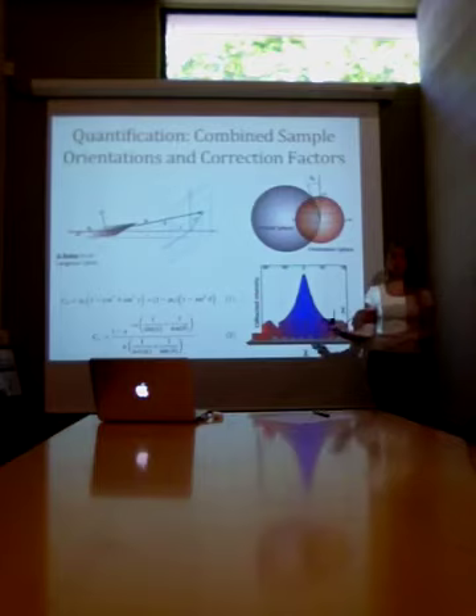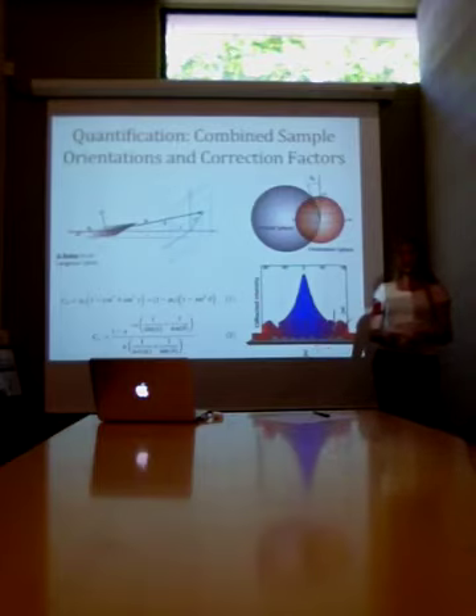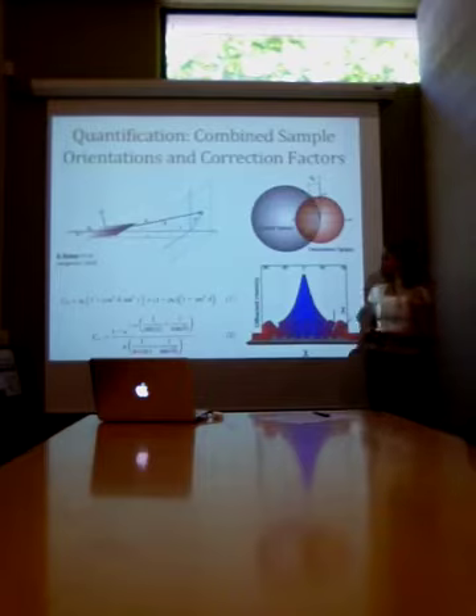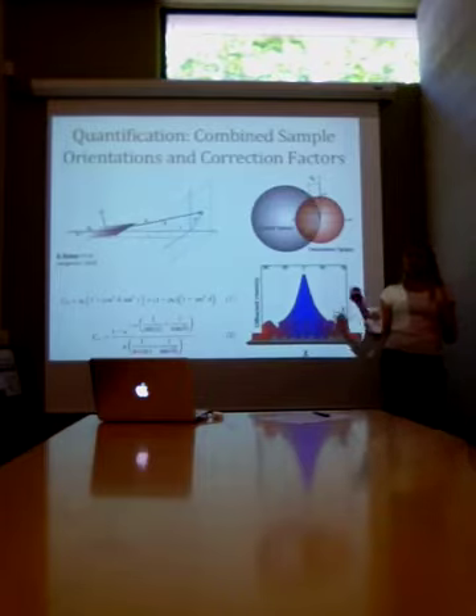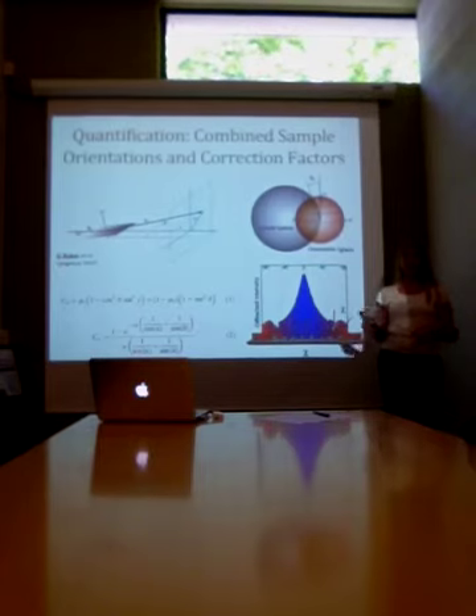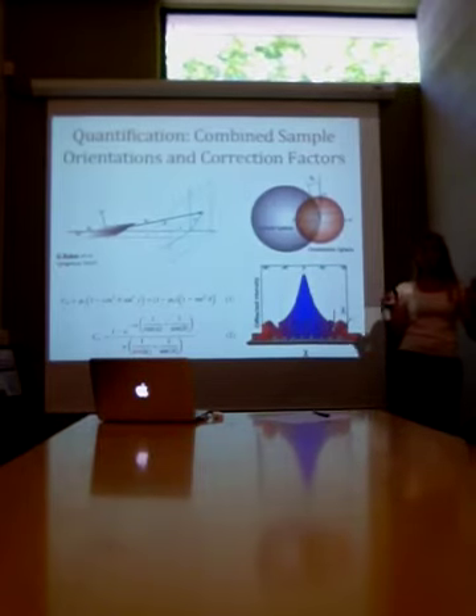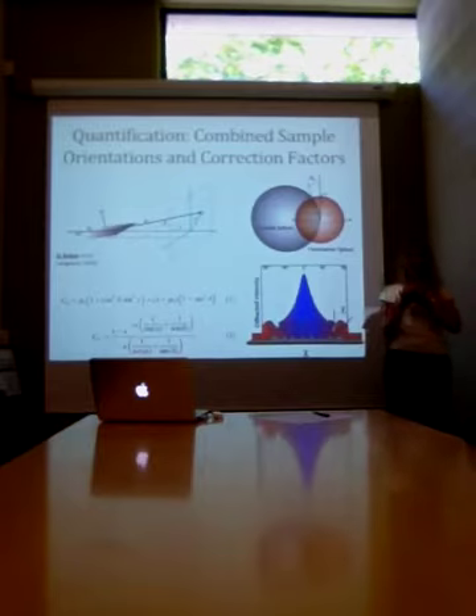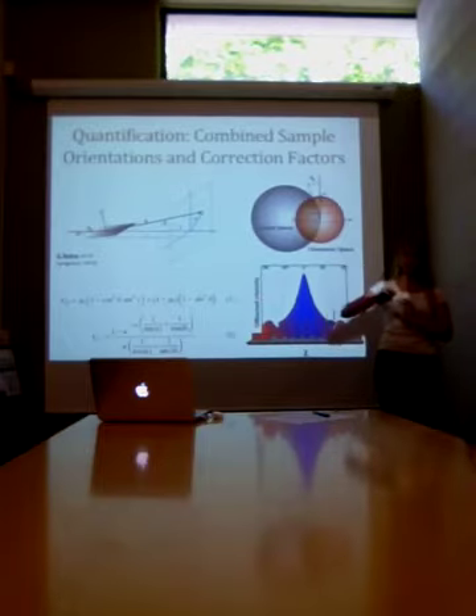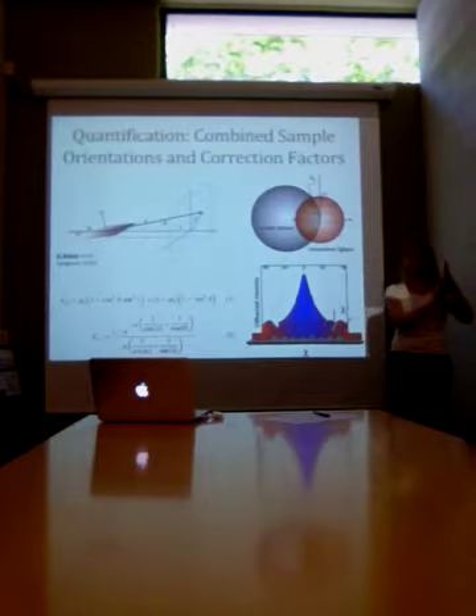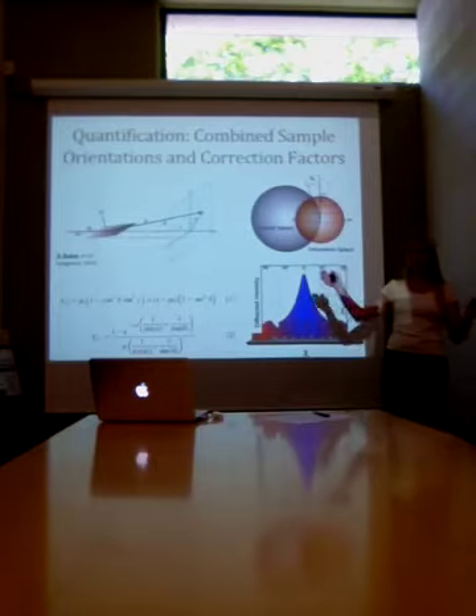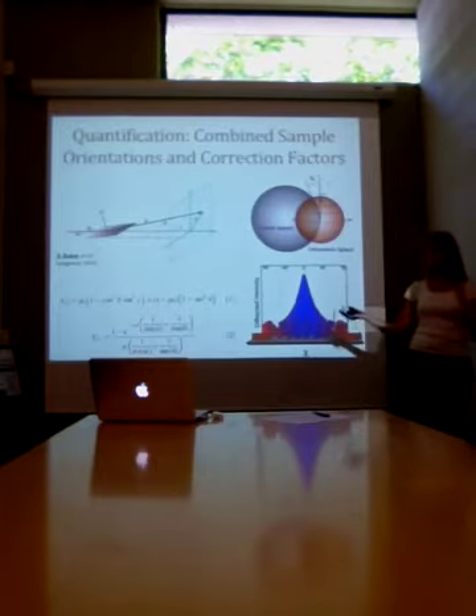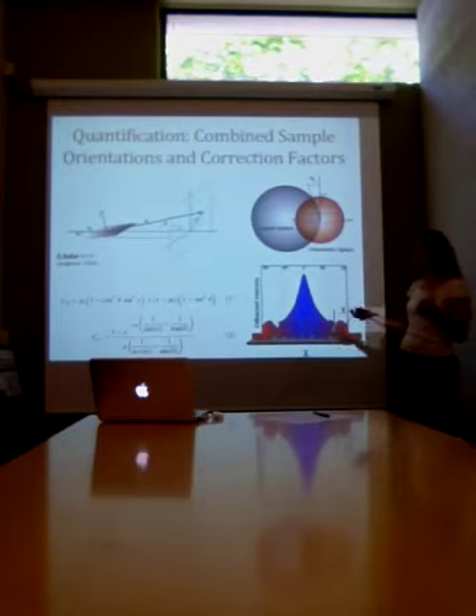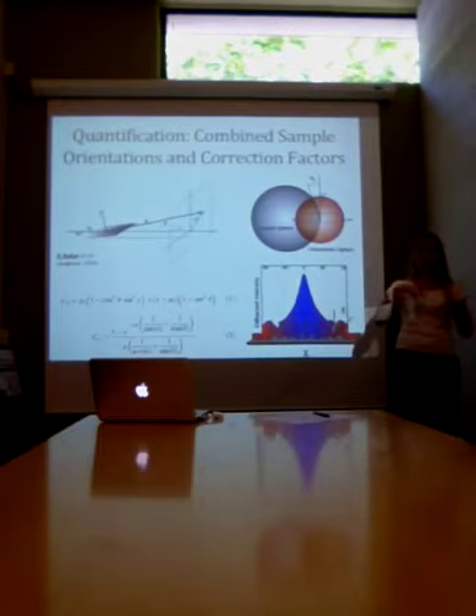People had used the same sort of technique to look at things qualitatively before, but they had never been able to quantify it. So after studying this for a while, we found that we needed to take this diffraction data at 2 sample geometries, one at grazing incidence and one in the specular geometry. We then stitched these 2 data pieces together, and then we had to apply 3 correction factors. One correction factor accounted for the fact that diffraction is happening in 3 dimensions, but it's being projected onto a 2-dimensional flat plate detector. The second correction is for any polarization of the incoming X-rays, which at a synchrotron radiation laboratory is roughly 98%. Finally, we had to correct for any absorption of those X-rays that was happening in the film.